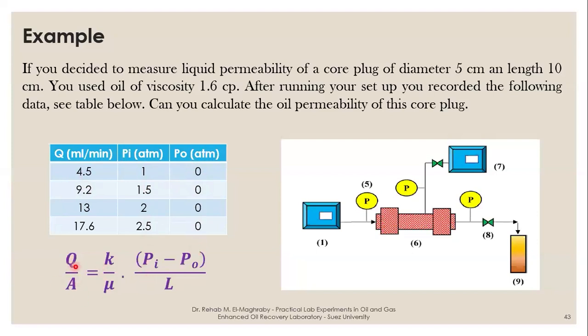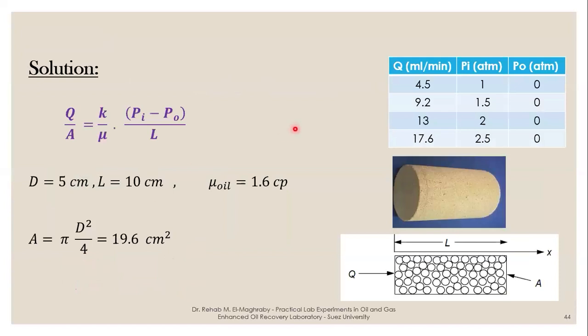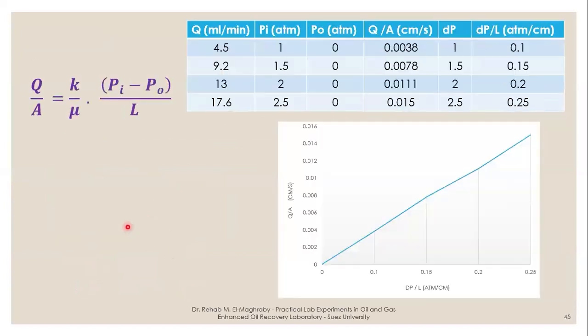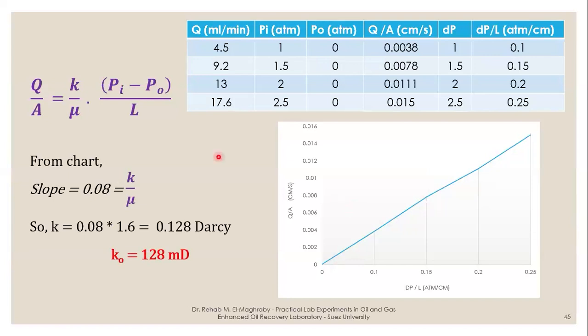So using this experiment and this equation, we can draw, and on the y-axis you have Q over A. So you calculate using the data. You calculate the A, then divide Q over A. You have different data and a straight line. You can measure the slope of this straight line and get the liquid permeability. In this case, it's oil permeability.